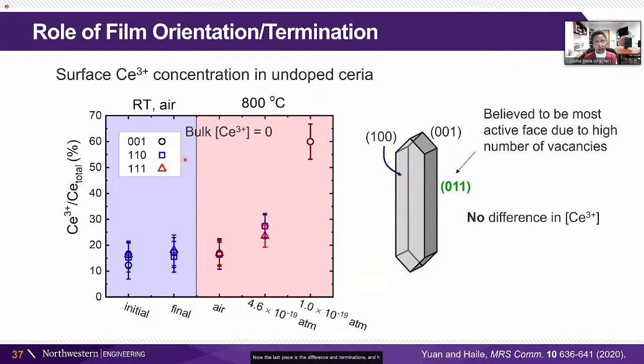And here we have 3 different terminations measured. And you can't even see the difference in the data points. They fall right on top of each other. This is at high temperature under air, high temperature under nominally reducing conditions. And this is just one of the measurements of the 001 orientation that we did under even more reducing conditions. They look exactly the same, initial, final. So we know there's no evolution of the sample over the course of the measurements. So this is a real surprise.